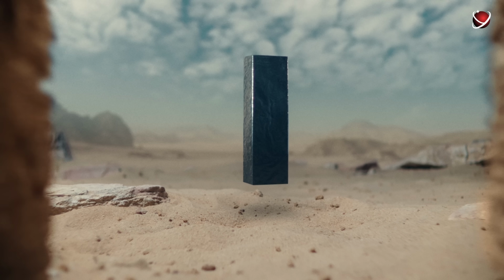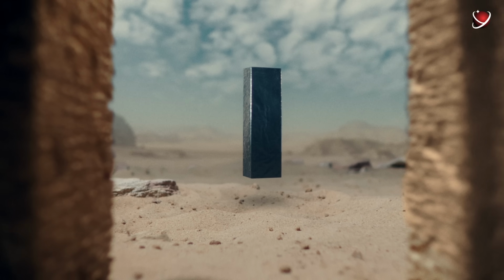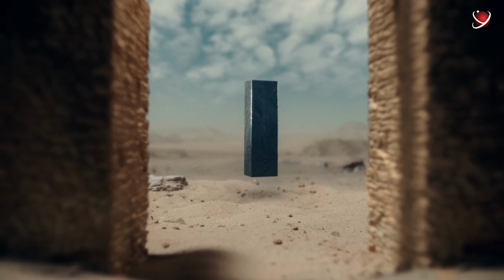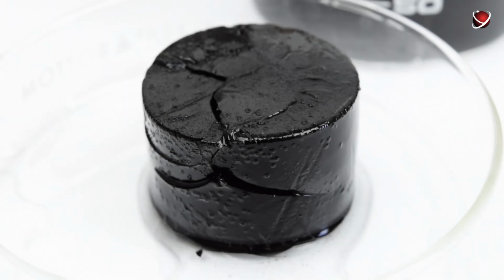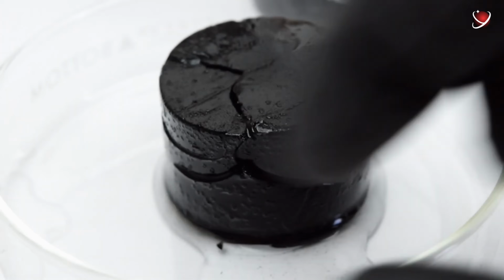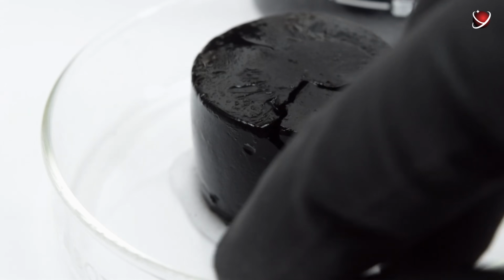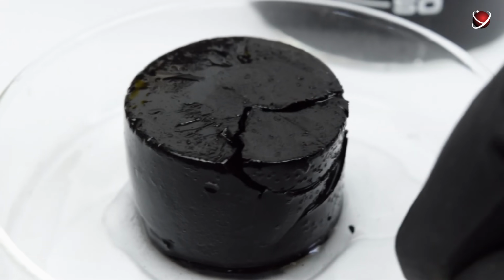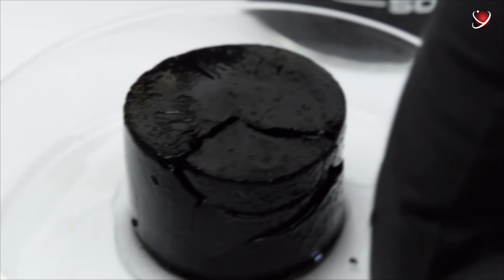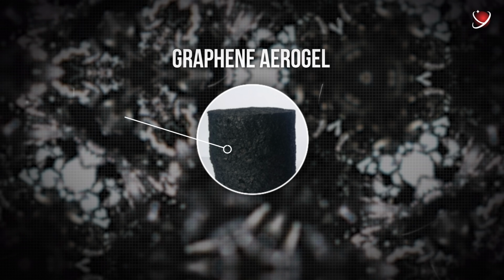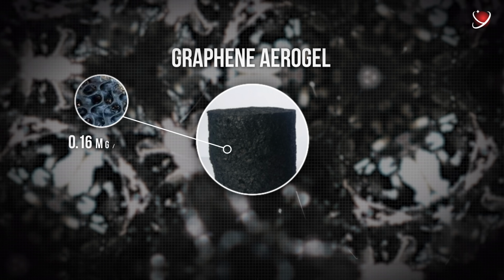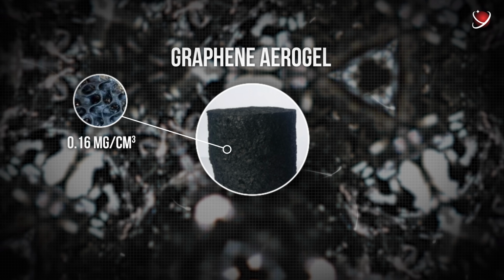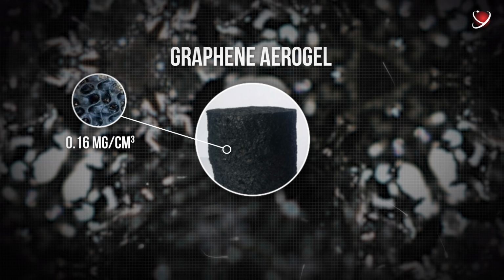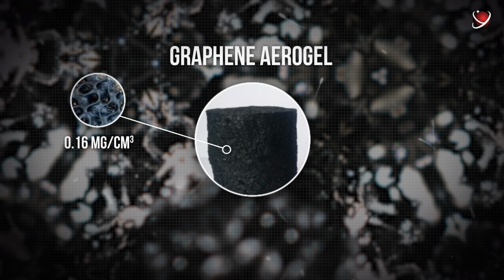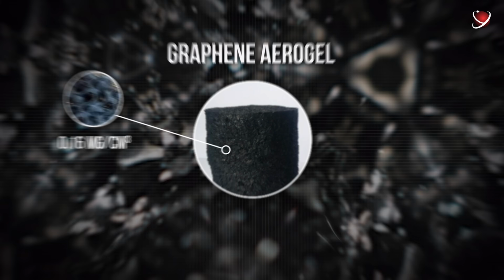It seems pretty tempting to combine graphene's strength and aerogel's lightness into one material. Well, Chinese experts already have a practical answer to this question. They've created the world's lightest solid material, graphene aerogel. With a density of only 0.16 milligram per cubic centimeter, its vacuum-filled variation is 7.5 times lighter than air. Without air in its pores, the material would simply hover.